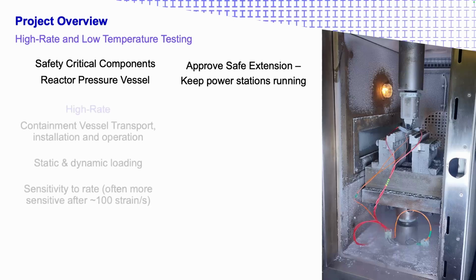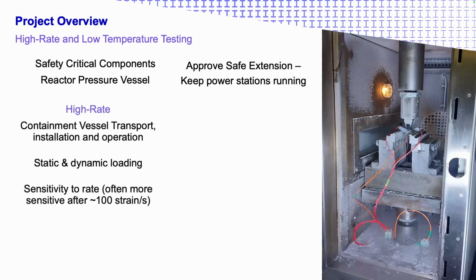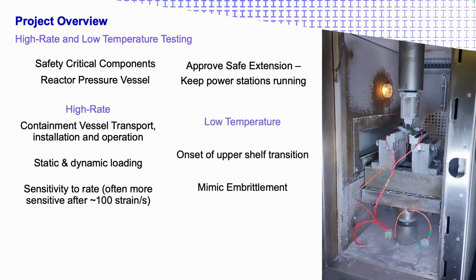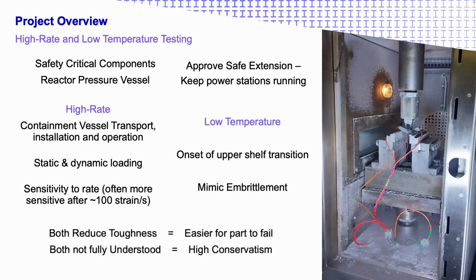Two key areas then is the rate that those sorts of things are experienced, the strain rate experienced. High strain rates have quite a high area of uncertainty through testing. So reducing that, improving our level of conservatism required. And then also low temperature testing. Low temperature for me, meaning onset of upper shelf transition. Over time, this may be a high temperature, but for the material that I'm working with, it is a low temperature. So both of these areas, we're working on understanding them better to ensure that we're safely using these materials as they can do.